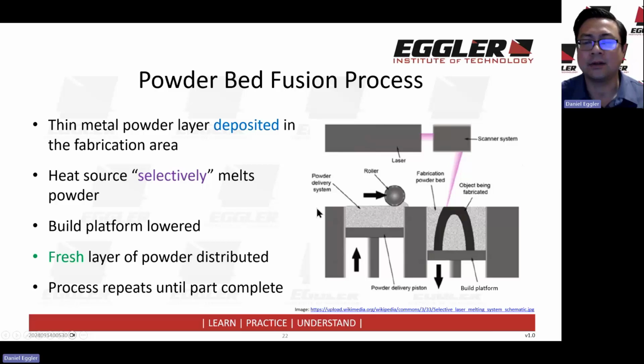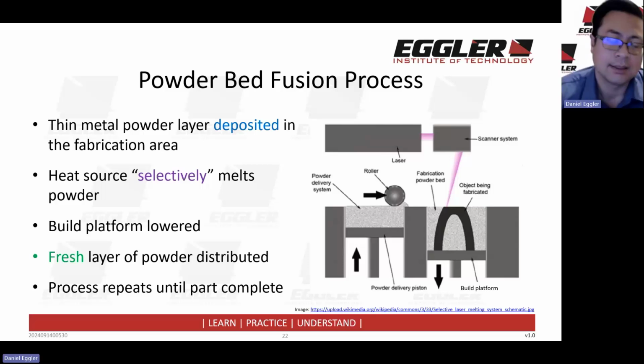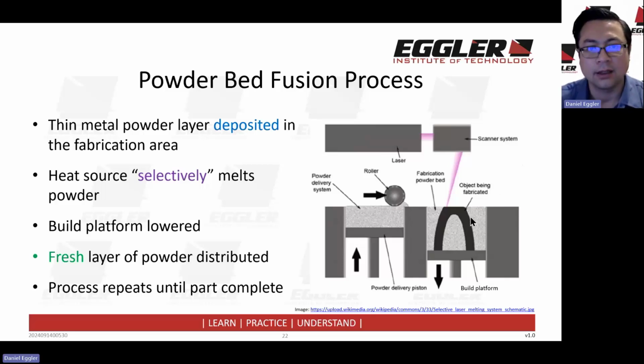I will also point out that when it comes to additive manufacturing, there is a lot of concern, particularly around metal additive manufactured parts, particularly because of our experience with HAZ, right, or heat affected zones from welds. So we know that these form structurally, these are the areas where during test and evaluation, these are selected for special attention because these form weak points. So we are always testing the welds for the weak points. And at first blush, powder bed fusion feels like a welding process, right? It's almost like millions and millions of welds, mini welds to create a part.